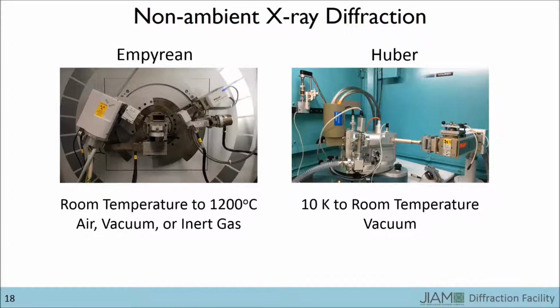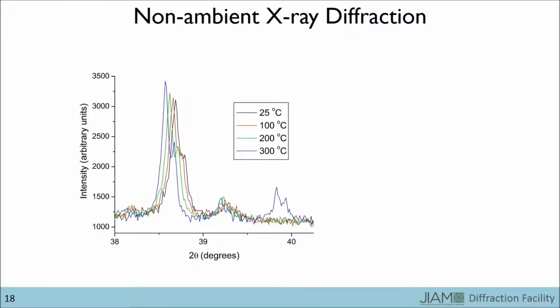Today, I'll show you 2 types of high-temperature experiments performed in the JIAM Diffraction Facility. The first is an equilibrium experiment investigating a sample's phase transformation, and the second type is a kinetic experiment of the synthesis of a compound from starting materials. As the compound for the first example has a rather complex pattern, this figure shows only a small region for clarity. In this experiment, the temperature was increased to a desired value, and the sample was allowed to reach equilibrium before the data were collected.